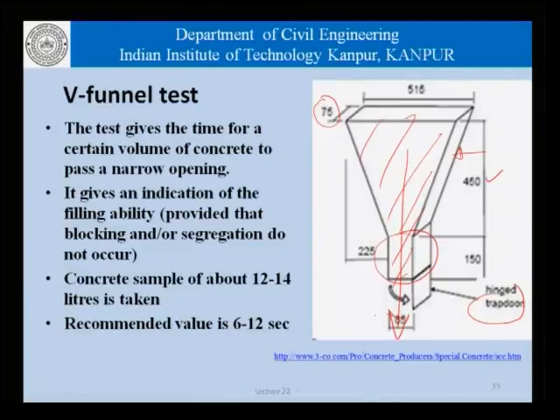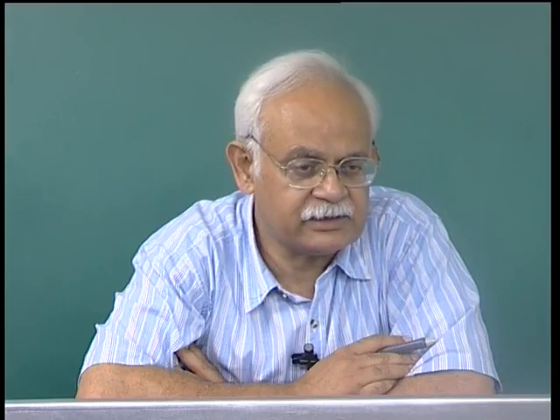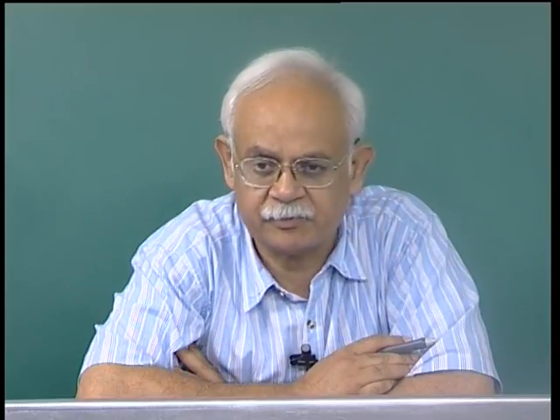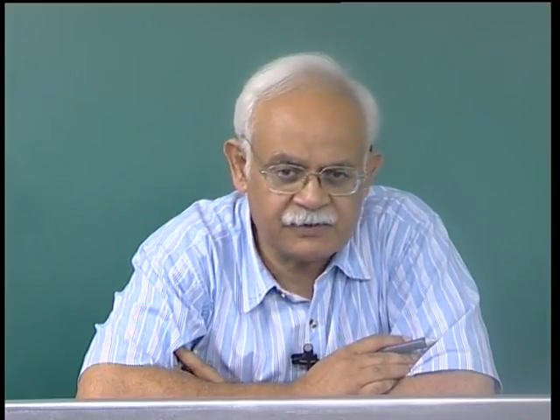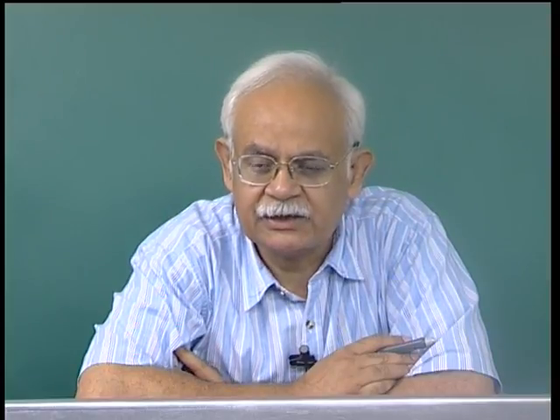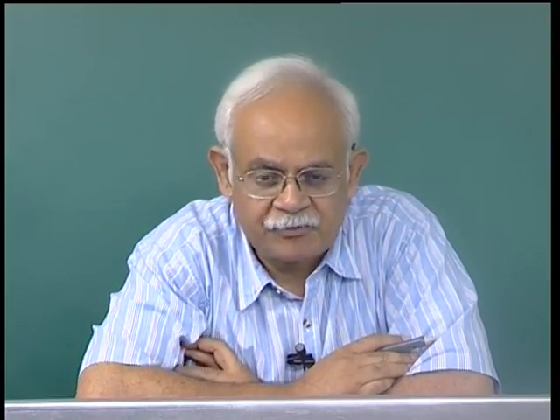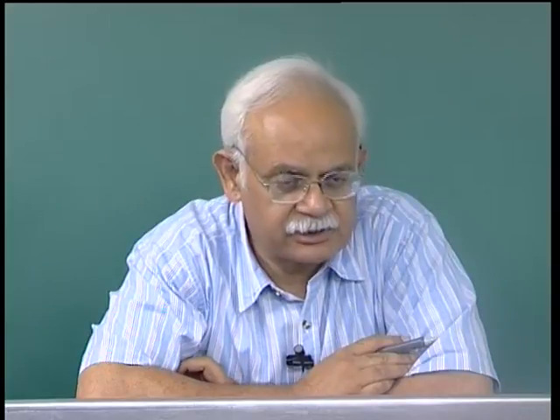the V funnel time. Now, once the concrete is flowing from a larger cross sectional area to a smaller cross sectional area here, the possibilities of aggregate interlock can be easily checked, and that is something which the slump flow simply cannot do. The slump flow therefore is the measure of the unrestricted deformability, whereas a test such as the V funnel helps us evaluate the concrete from the point of view of aggregate interlock and so on.